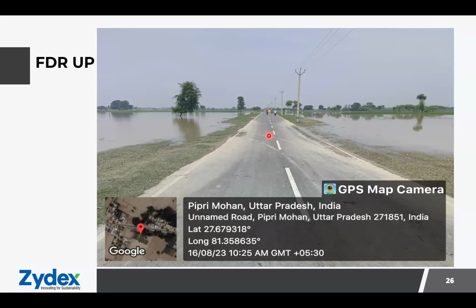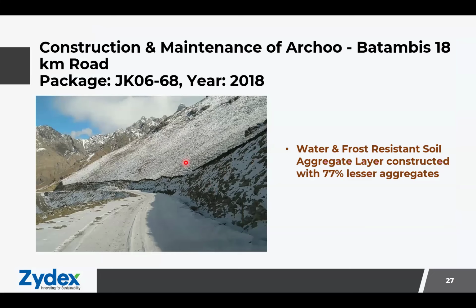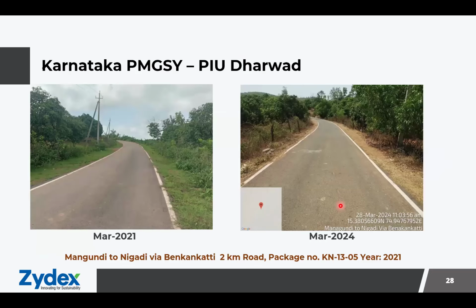modulus value. Further, the technology works in heavily frost-affected regions, where you can see snowy regions completely surrounding the pavement layer, but it's still performing under good conditions. In both the conditions, we have replaced the aggregate by almost 77% and have used marginal soils or borrow materials which are available locally. Further, this is another project from Karnataka, a PMGSY road. Here we can see after 3 years, there's hardly any degradation that has happened, and the pavement has been performing very well, even after 3 monsoon seasons.